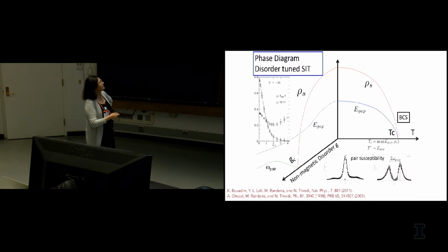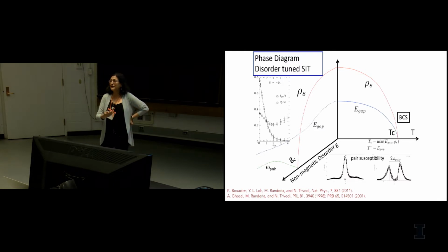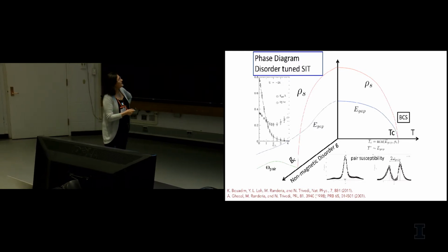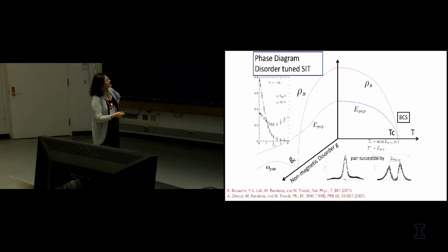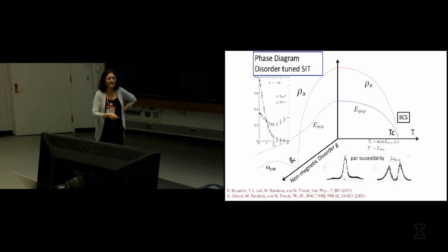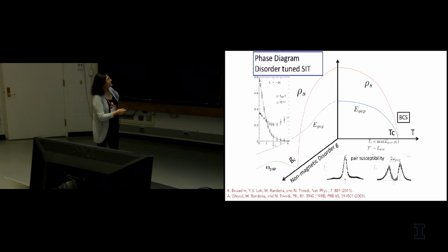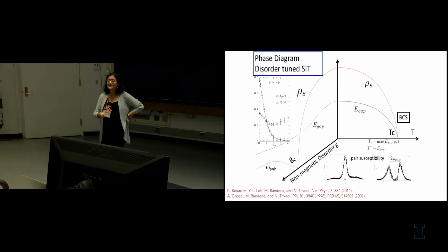So in other words, if you were looking at the behavior in temperature, then you would see that Tc is given by the minimum of the gap and the superfluid density. And at low disorder, clearly the gap is the lower energy scale, so that's essentially fitting the BCS expectations. But closer to the critical point, where the gap becomes the higher energy scale and rho s is dropping, now Tc is governed by the superfluid density.